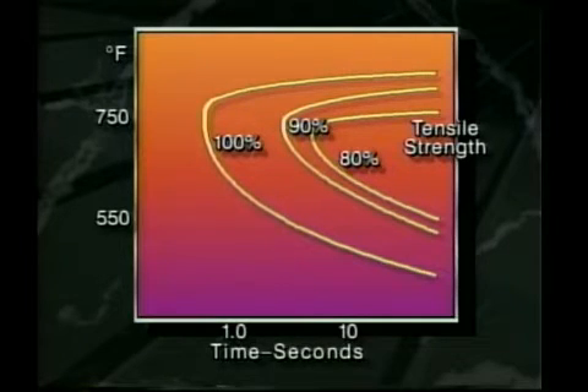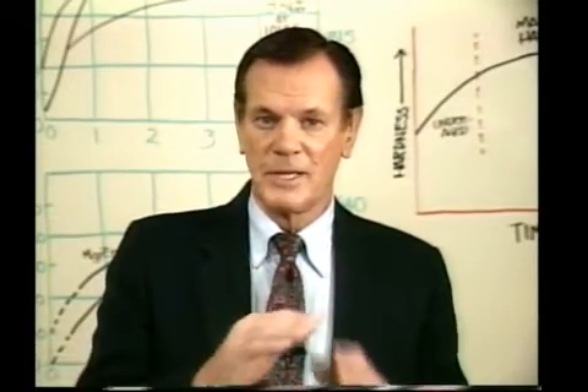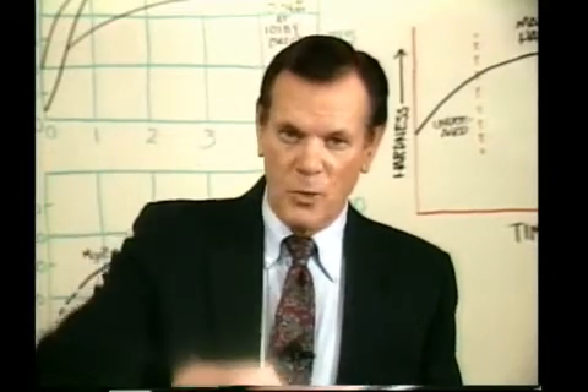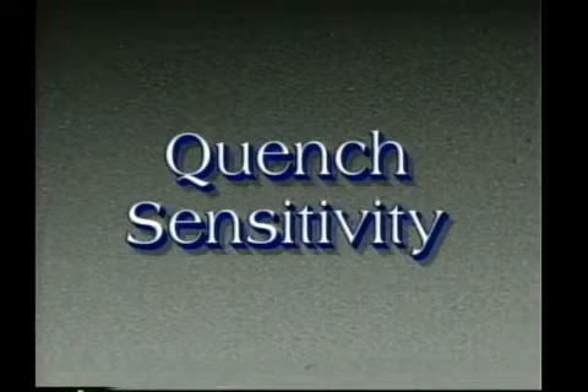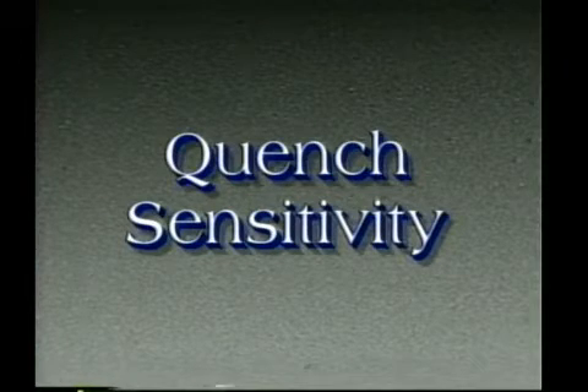It should be noted that in holding both at a higher temperature, such as 800 degrees, or a lower temperature, such as 400 degrees, the property loss was not as large as at 675 degrees. From this study, it was demonstrated that the critical temperature range for quenching aluminum alloys is between 750 to 550 degrees. In this temperature range, the atoms diffuse and precipitate rapidly, and a resultant loss of tensile properties will occur. Thus, in the quenching process, it is important that the metal be rapidly quenched through this range to retard the diffusion and precipitation reaction.